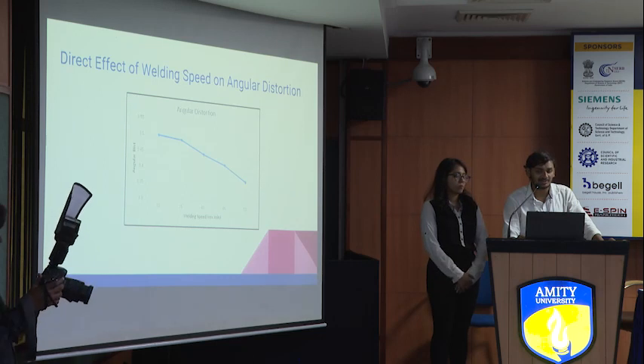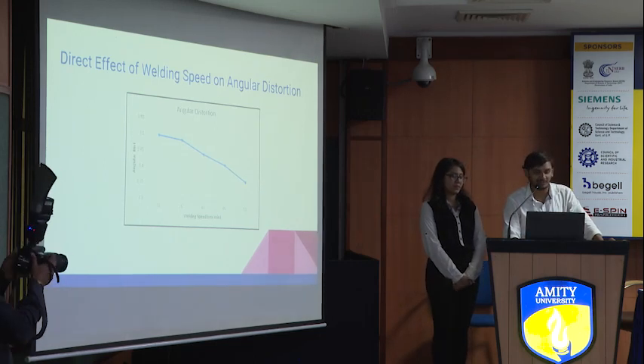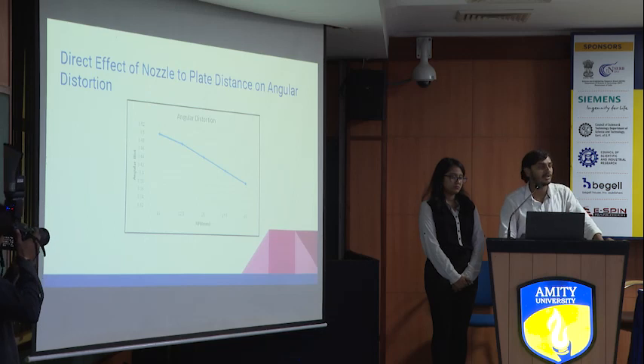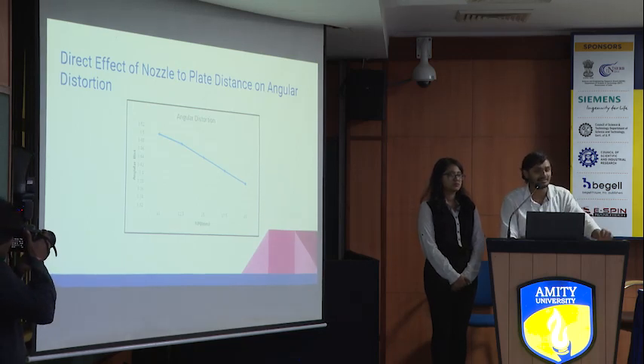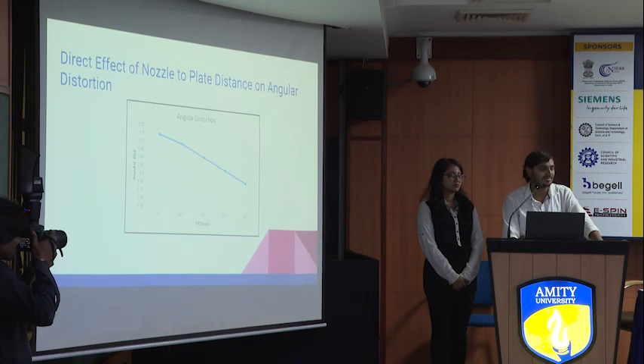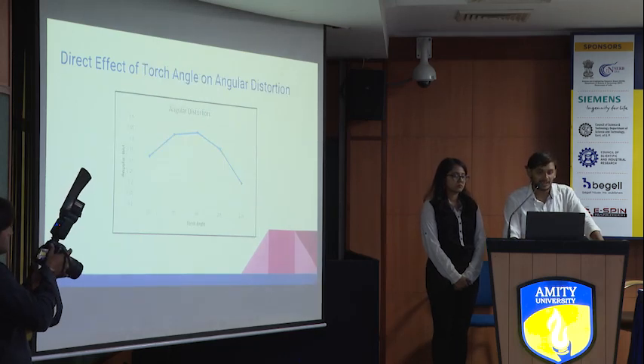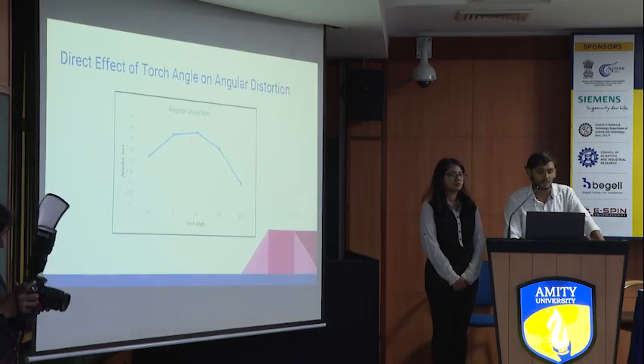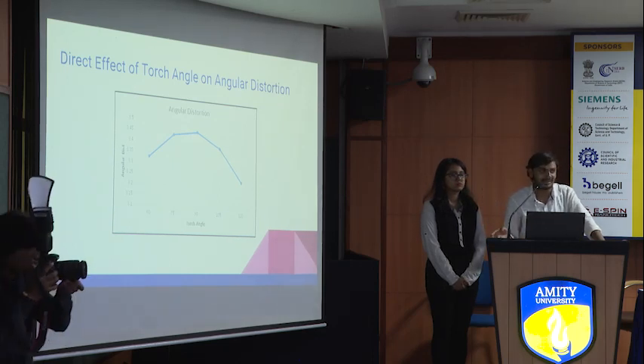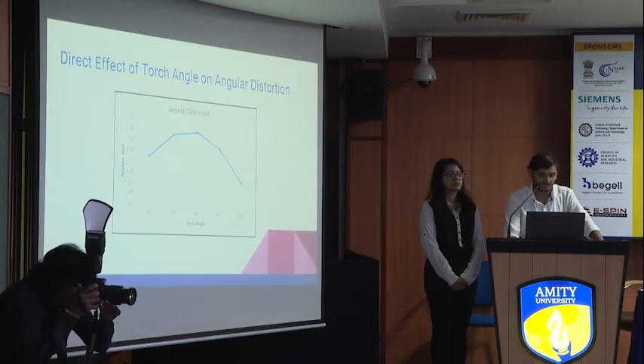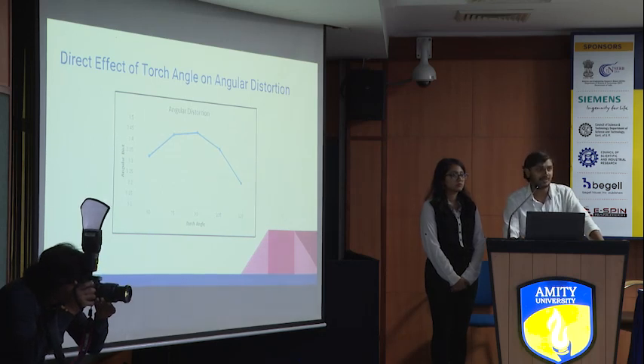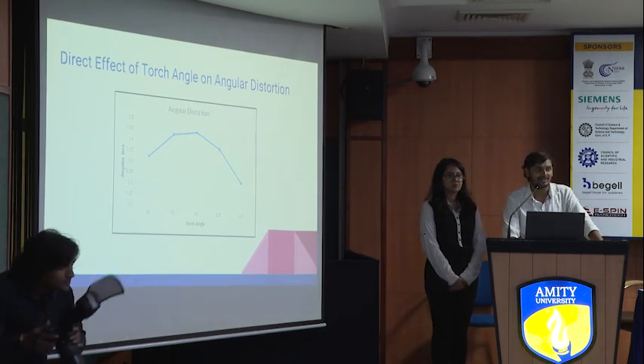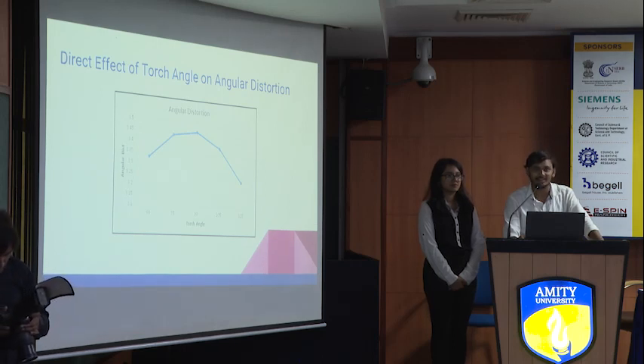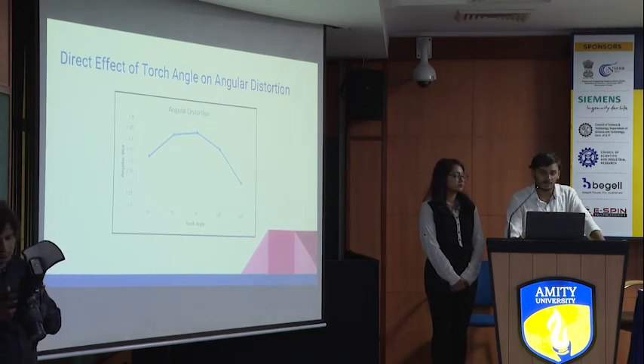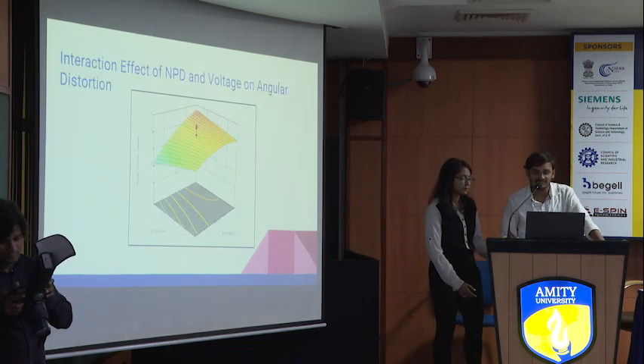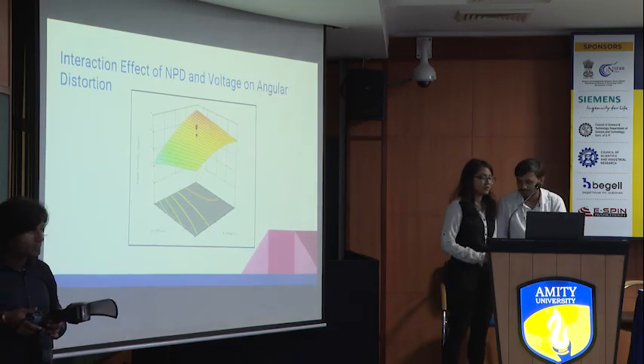By increasing the welding speed, the angular distortion was decreasing, and by increasing the nozzle to plate distance, that is the arc distance, the angular distortion was significantly decreasing. And by the direct effect of torch angle, we can see a slight increase and then a dip in the angular distortion. After the single factors, we took 2 factors at a single time to get a relation between them. So I would like to ask Drishti to explain these plots.